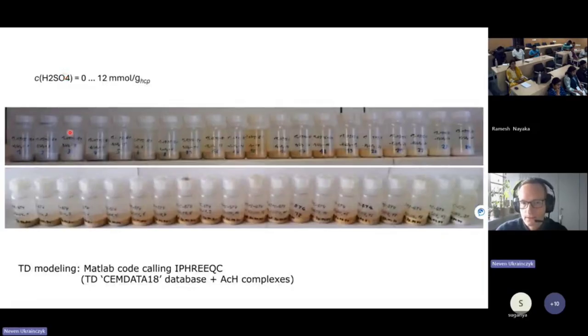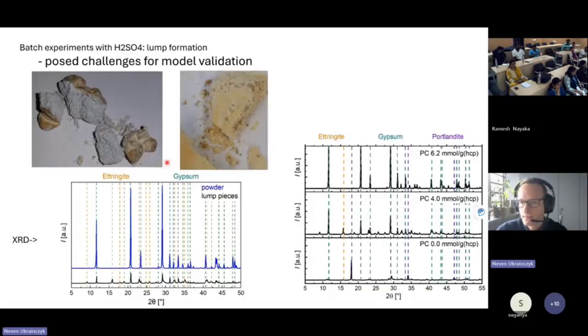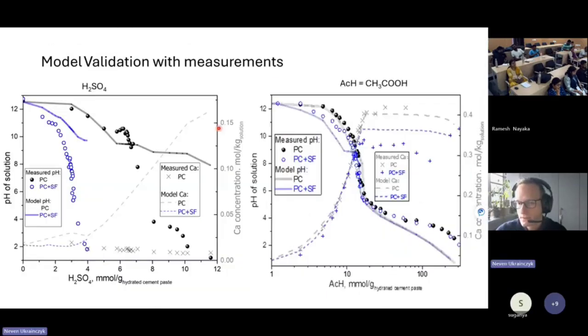Also for sulfuric acid, this is acetic acid. With sulfuric acid, there was this protective layer, so we could not really get the equilibriums, because that's the challenge. With acetic acid, you can see the model. So just by pure thermodynamic modeling, just by chemistry, fundamental predictions, without any fitting parameters, we were able to reproduce the experimental results. So this was a very nice success.